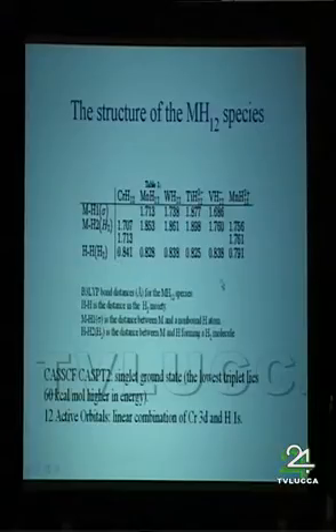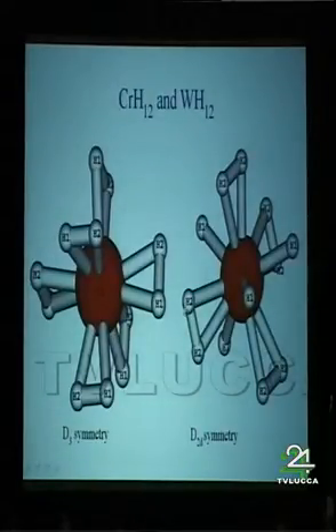So this long bond distance should be a fingerprint of the fact that you don't just have a hydrogen molecule which happens to be close to a metal, but you have some binding between the metal and the hydrogen. And the ground state of this molecule is closed shell, a singlet. These accurate calculations told us that we don't have to worry about a close-lying electronic state. These are two of these molecules, how they look like. So chromium H12 has 6 H2 moieties, which are bound to chromium, while in tungsten H12 we have 4 H2 moieties and 4 single hydrogen atoms bound to tungsten.